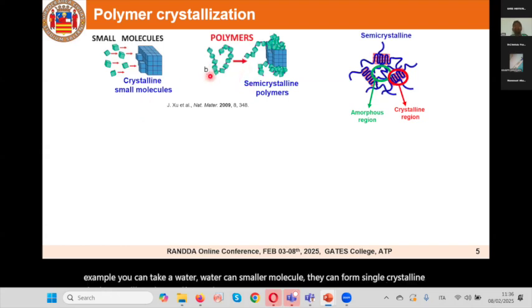Whereas if you take the polymer, it is a very long, big chain molecule. This polymer has a complex entanglement. Due to that, this polymer cannot form a completely crystalline structure. Instead, it forms a semi-crystalline structure, as we showed in the schematic of the semi-crystalline polymer. So that is the major difference between the small molecule and polymer in their crystallization process.